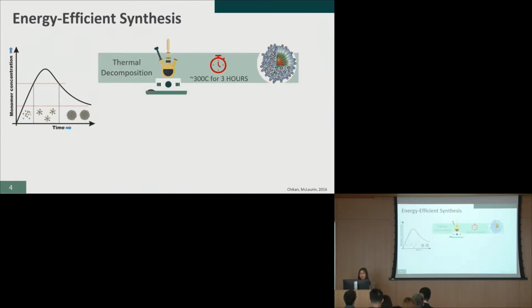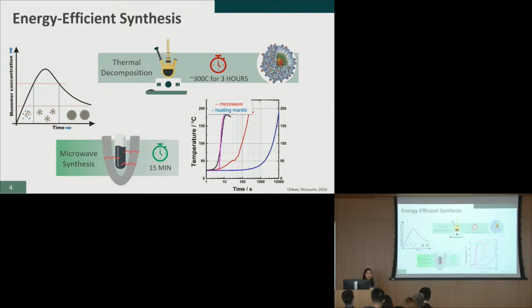But the traditional method, which is called thermal decomposition, requires us to leave these particles in solution at 300 degrees for 3 or sometimes even 4 or 5 hours. This is highly energy inefficient, and we're looking for new ways to make the synthesis more efficient for higher scaling up of nanoparticles. So one way that has been very underdeveloped that I'm looking into right now is called microwave synthesis.